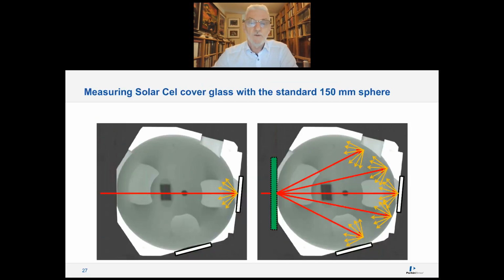The result comes in the next couple of slides, but I show you one of the most important reasons for this discrepancy, which has to do with the following. Here is a standard integrating sphere accessory with the top half removed. It has a spherical cavity of very white diffuse Spectralon material. With the calibration of the baseline of the instrument, you have the left situation where the beam of the spectrophotometer, without interaction with a sample, hits the target on the back of the sphere, which is normally a reflection target.